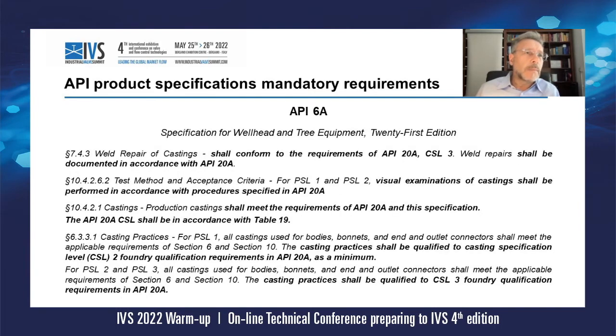Here is another sample where API asks for mandatory requirements of the 20 series. Once again, API 6A specification for wellhead and tree equipment, 21st edition, where repair of casting shall conform to the requirements of API 20A CSL3, where repair shall be documented in accordance with API 20A. Test method and acceptance criteria for PSL1 and PSL2: visual examination of casting shall be performed in accordance with the procedure specified in API 20A. Production casting shall meet the requirements of API 20A and this specification. The API 20A CSL shall be in accordance with Table 19.